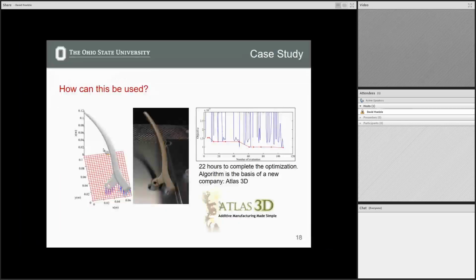So here's an example of a part that I passed around earlier in the class. What you're seeing here is not actually the part that was passed around. This one is the one that printed without defects at all. There was actually a small little defect on the base of the one that I handed around. But what we found here is that this was what the algorithm determines to be optimal. And what it's doing is it's taking a pretty long, slender part, and I'll show examples of cases where this fails in the next slide.